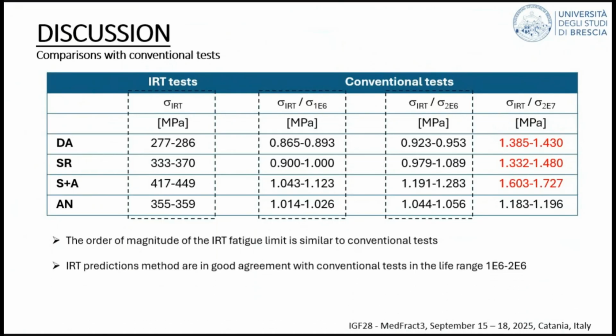What is very different is what happens if you compare the prediction with infrared thermography and what happens at 20 million cycles. Because in reality, what we observed is that in some cases we had failures for load levels, stress levels, lower than the predicted fatigue limit. So this was a puzzling result, but we tried to explain it with two different aspects.